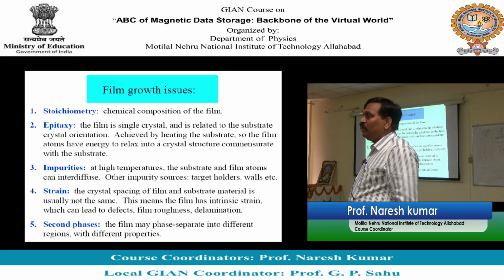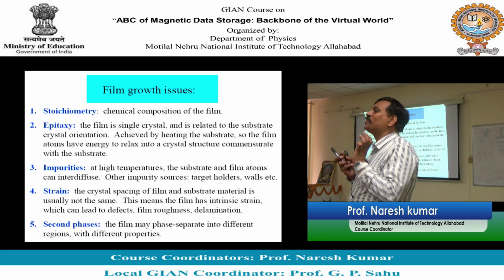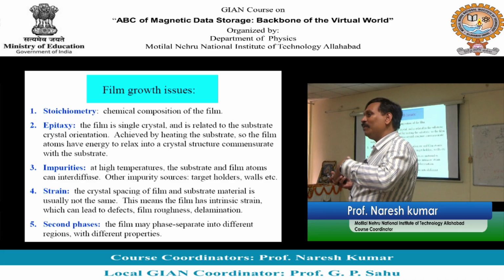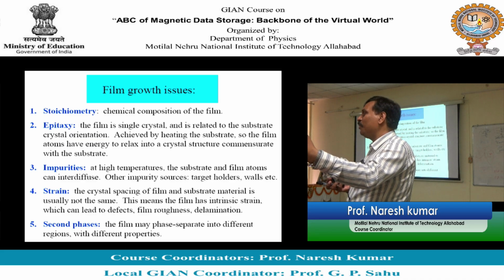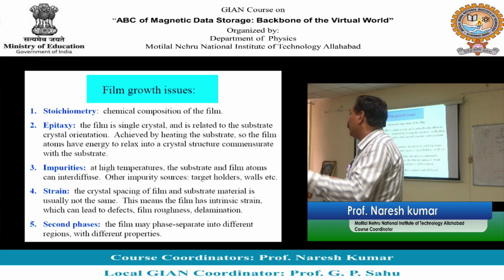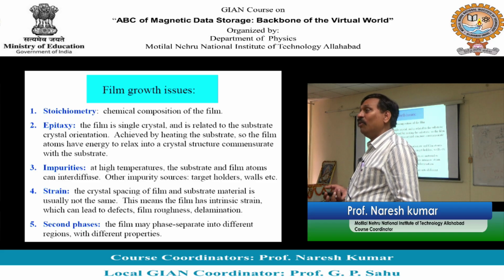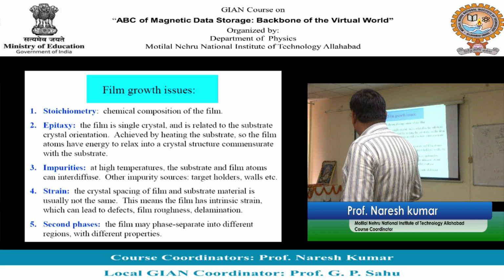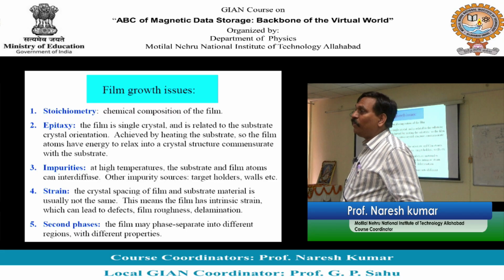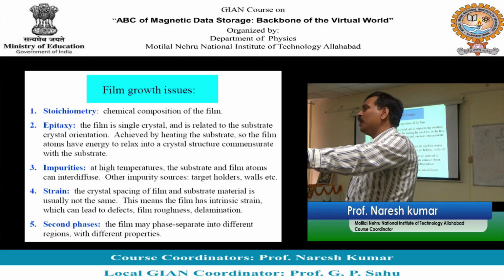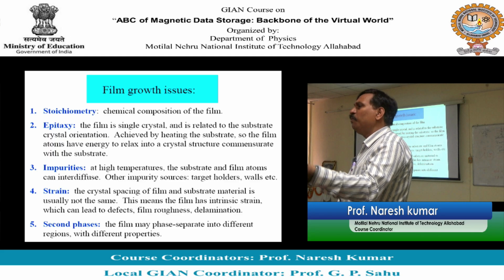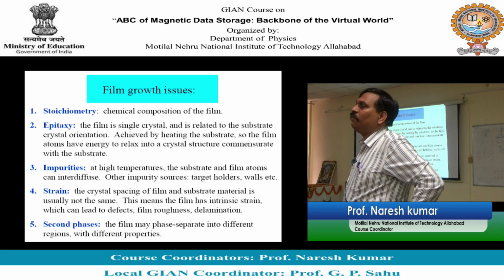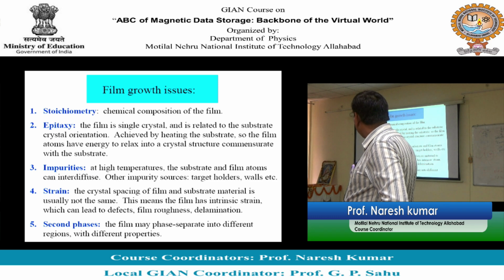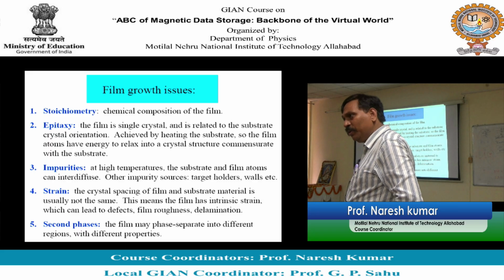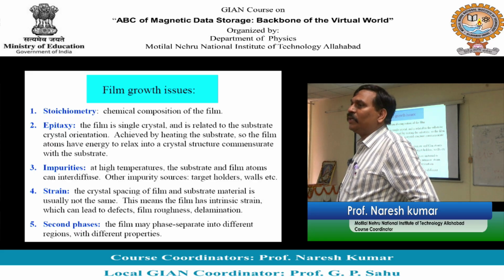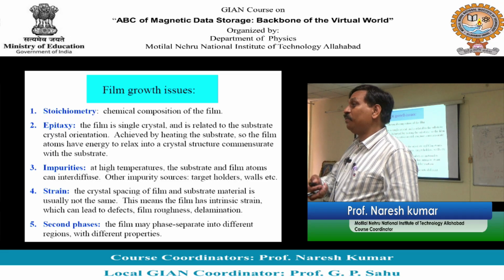Strain. Depending upon how my substrate is selected, my film can have a different lattice parameter, which may not be the same. So they are either compressed or expanded. So they may be under strain or stress, and accordingly properties may change. This is another problem, second phase. Though my target is of some chemical structure, when you make a film, you have additional phases coming into it. So you need to overcome all of them. If you could take care of all of them, then perhaps you can get the desired thing. But it gives you the opportunity to play the way you wish, right?